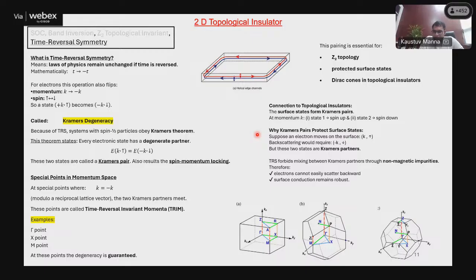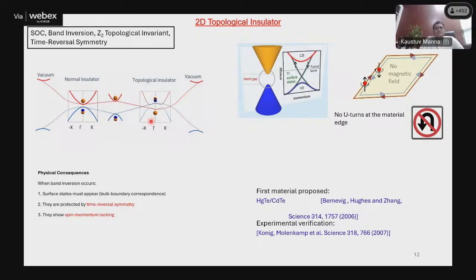So I have already discussed this and time reversal symmetry. Now you see how the Z2 invariant induces a surface state. In the bulk band, you already have the band inversion, whereas outside the material it is, let's say, vacuum or air, anything. This is a trivial insulator. So if you connect excitation from conduction band to conduction band or valence band to valence band, because of the band inversion, part of the conduction band has gone into the valence band, whereas part of the valence band has gone into the conduction band. So when you connect it, you see that there must be a point where these two parts cross each other. That crossing is actually the surface of the material, where irrespective of outside being gapped and inside being gapped,